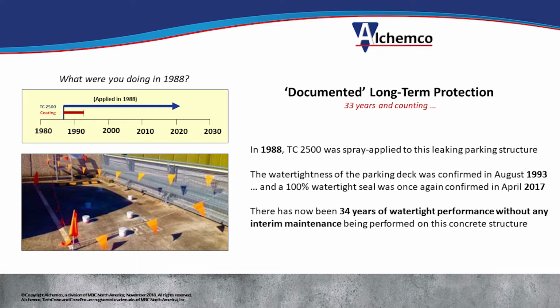And then they did a new test 29 years later, so in 2017. And so 29 years after the original application, the area was still watertight, and the cracks that were leaking back in the 80s were still dry. So nothing was done. We had a testimony from the owner of this parking structure. So nothing was done, and the area was still watertight.